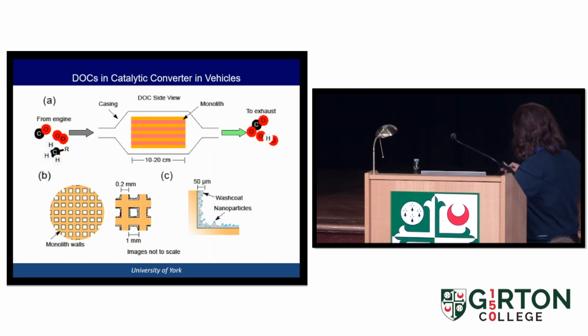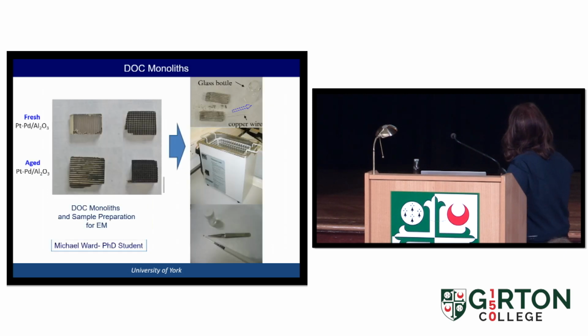And this is actually what the catalysts look like. You can see this is a real catalyst, about 10 to 20 centimeters across. The exhaust comes in over the catalytic converter, and then we get some of these oxidized products. We want to convert carbon monoxide into carbon dioxide and nitrogen oxides into nitrogen. We looked at the fresh and aged samples. This is the bimetallic system, platinum, palladium, and alumina. And you can see after 30,000 miles of driving, the catalytic converter becomes very black.